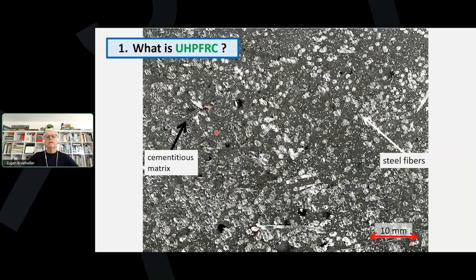What is UHPFRC? You can see here on this photograph, which is a cut through UHPFRC, that actually we have dark areas and white areas. Dark is the cementitious matrix. You can imagine that there is a significant amount of cement and other fine particles, maximum particle size of 1 millimeter only. It's a bit like ceramics. So this is the cementitious matrix, and the white dots are steel fibers. Steel fibers that are very thin, like needles, 0.2 millimeters thin and about 15 millimeters long. And we have a huge amount of those steel needles in this cementitious matrix. This is UHPFRC.